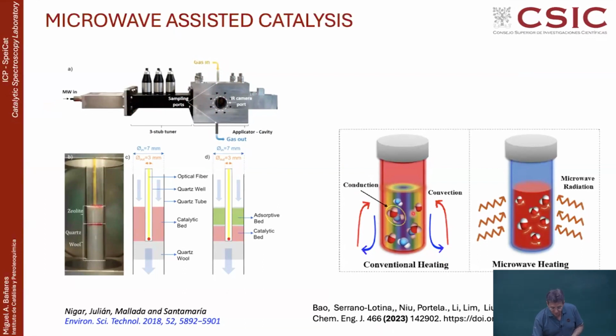This is the temperature profile in a normal heating where the heat is coming from outside, and this is on a microwave heating. So in the case of a conventional heating, basically, you will be heating from outside in until everything is more or less heated. And that can be not very efficient. A lot of energy is lost in the diffusion. On the other hand, in the case of microwave, because the microwave penetrates the material, it's heating all the material, and it's providing a more efficient heating mainly from inside out.